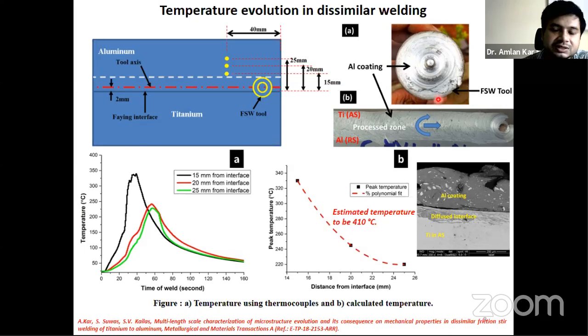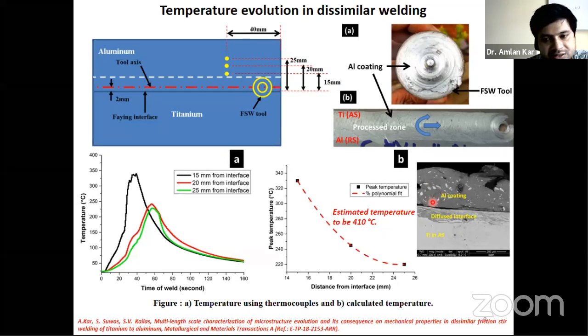But at the edge, you can see there is not much sticking. But the velocity gradient is very, very high. So the overall temperature, we are assuming, is more or less constant below the tool shoulder. And on top of the cross section, this is the cross section image, you can see that on top of the titanium there is a coating of aluminum. So there is interaction between titanium and tool, but this interaction is not constant, and we can say there is a limited interaction between tool and the titanium.